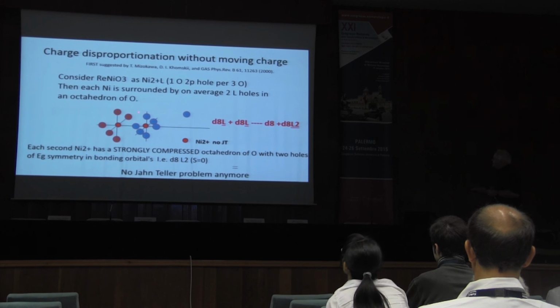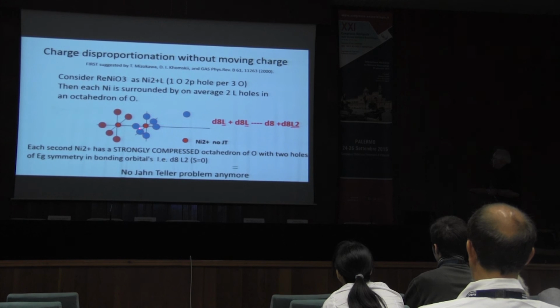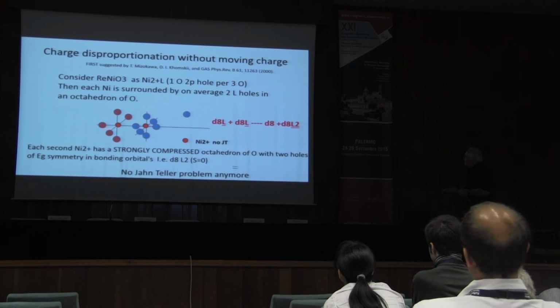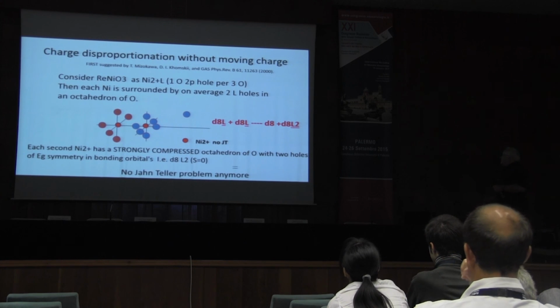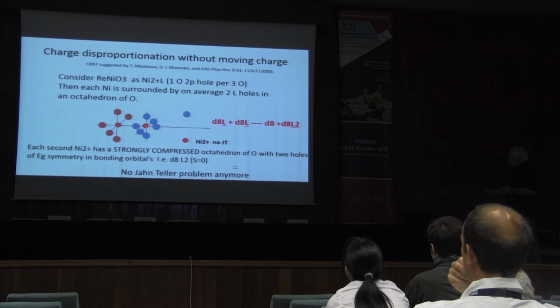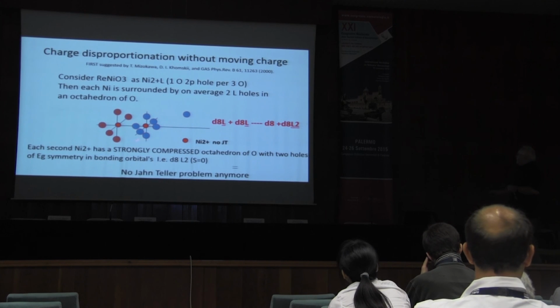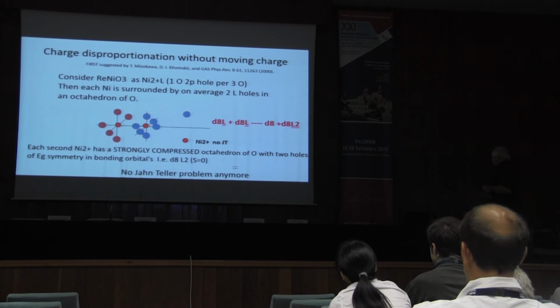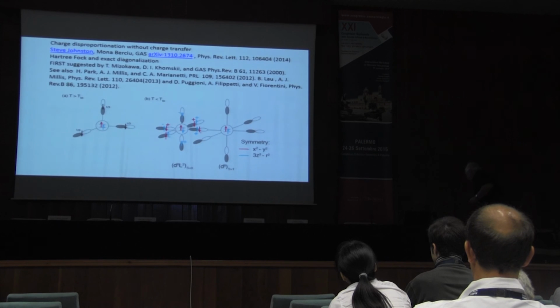So what happens is that you get collapsed octahedra, in which this bond is very, very strong with all of these holes in a molecular orbital, but now of octahedral symmetry rather than this square planar symmetry in the cuprates. And this bond length is very large, so that this nickel oxygen distance is very large, and that covalency is much smaller. The nickel is 2 plus with spin 1, the nickel is 2 plus with spin 1, but now very strongly covalently mixed over here. Okay, let's see if that actually can work with a theory.